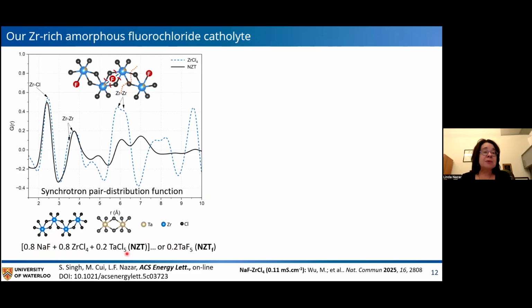And these components are important partly because they sort of dope the lattice, although it's not clear that one could call that doping, because it's an amorphous material. But they also are fairly low melting solids, which when ball milled effectively act as a solubilization matrix to solubilize these salts. And so that means that the ball milling process can actually be fairly short. And this has just come out in ACS Energy Letters, I think, today.